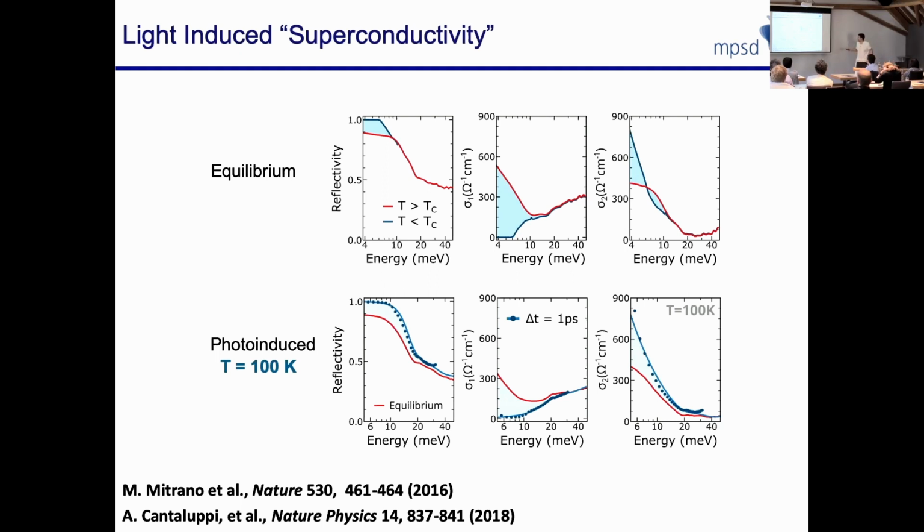So it's as if you were taking all this red spectral weight and condensing it down, with the right sum rules, to maybe not a pole, but certainly a peak centered at zero frequency. Of course, this peak is going to be broadened by the lifetime, so it's not really a pole. But if you think about the mobility, not the conductivity at constant carrier density, the mobility of this state is something like 15,000 or higher. So this is what was observed.